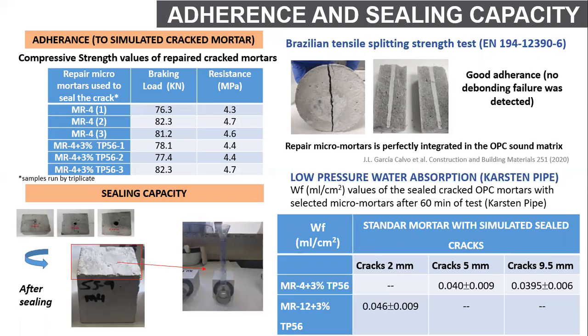Finally, the capacity of the sealing was also tested in the smaller specimens with the selected repair micromortar formulation. The sealing was evaluated with the low pressure water absorption test. As we can see in this table, the water absorption values are very low, lower even than the ones obtained in the traditional OPC standard mortars, and similar to those measured in the reference mortar, indicating that the repair micromortar not only has sealed perfectly well the crack, but also its water permeability is lower than in the original substrate.